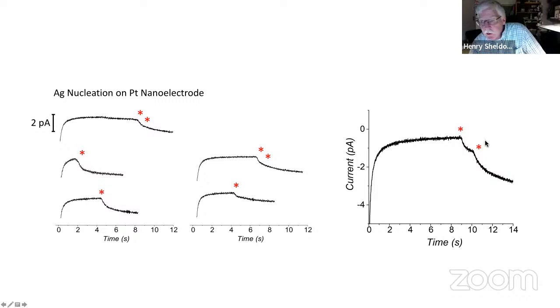And the number of nucleation events, when you do this experiment over and over, follows a Poisson type distribution, where for this size electrode, the most common outcome is you get 1 nucleus to form in about 10 seconds, sometimes 2, rarely 3, and sometimes you don't get any nucleation for tens of seconds, all right? It's all stochastic.